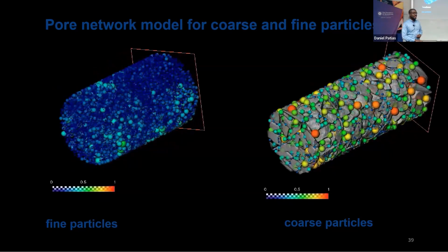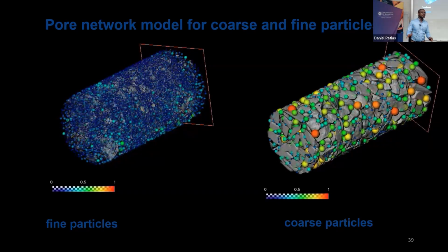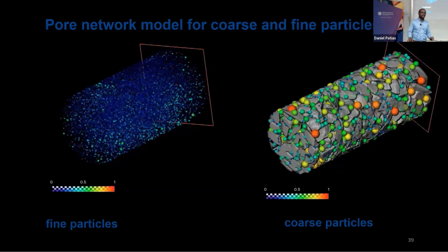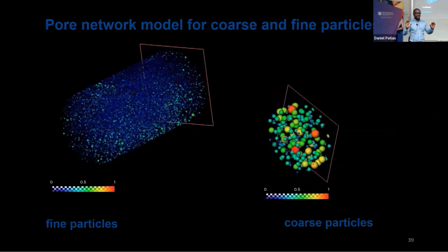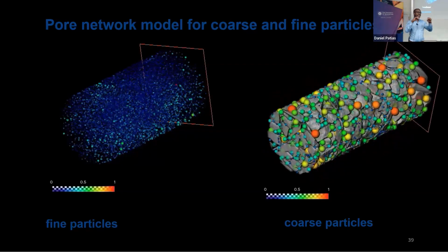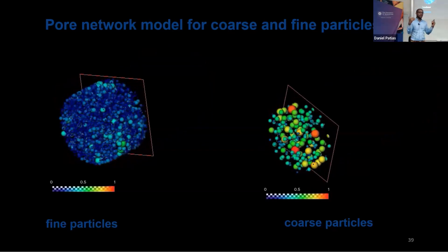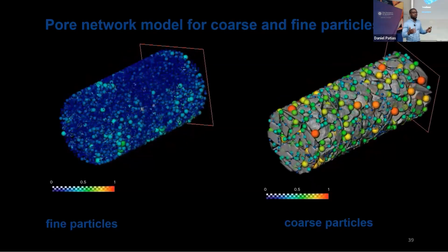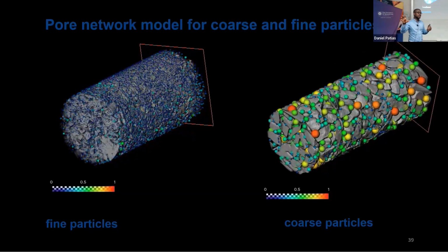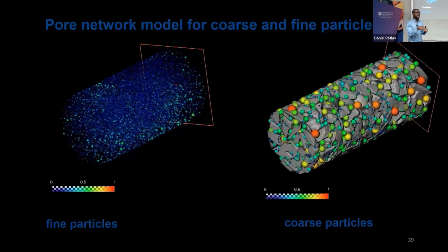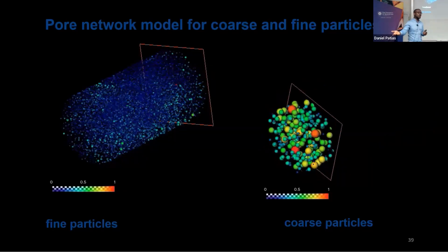With that, you can get something called a pore network. For a pore network, you're looking at a simple analogy: you have two balls and a stick connecting the balls. Your balls are your pores, the stick is the connectivity between the pores. This is important because there could be pores but no connectivity, and there could be connectivity but no pores.